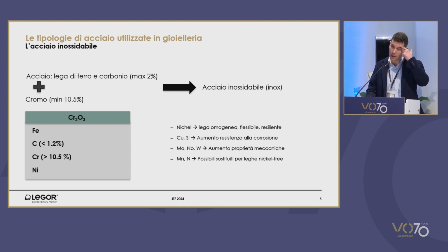It contains carbon and iron, carbon to a maximum of 2%. It is considered stainless when chromium is added in a percentage which shouldn't be lower than 10.5%. Chromium allows for an oxide being generated that actually makes the alloy self-passivating. So this coating, this layer of oxide, makes it less vulnerable to corrosion, and it is a barrier against the migration of the elements that are included in the alloy.